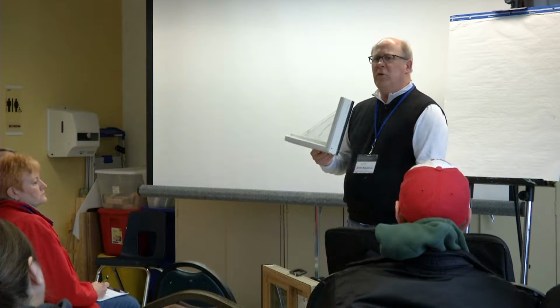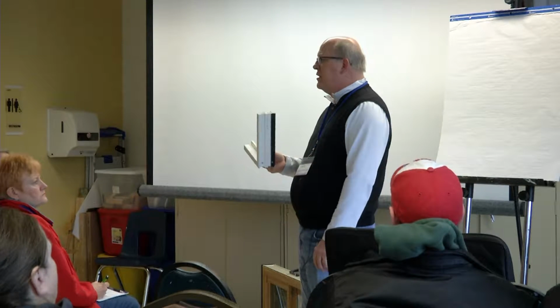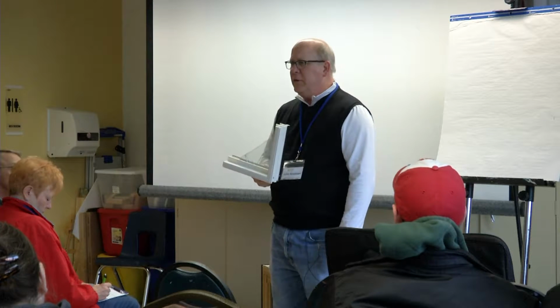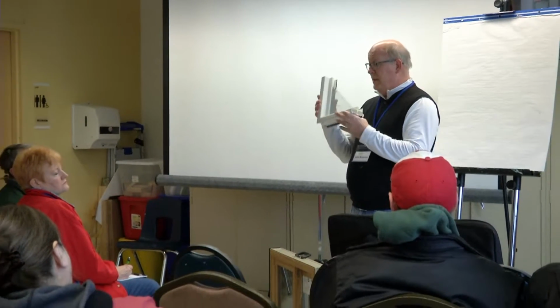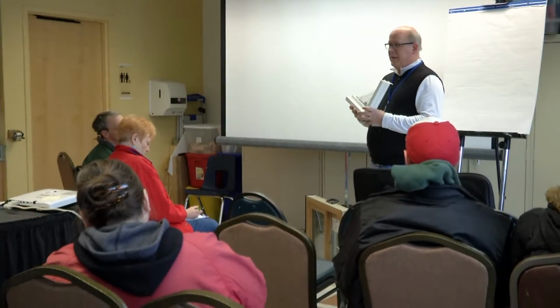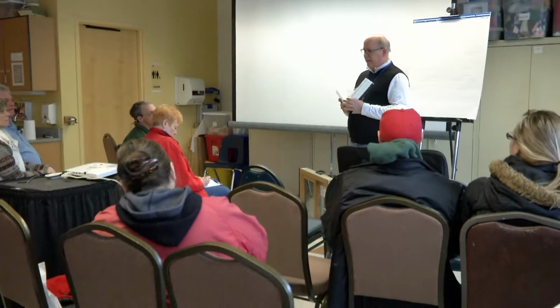Okay? So the reason you'd want to do fiberglass is that it's very strong, very durable. But it's not going to make things any more energy efficient for you, folks. 80% of our heat loss is through the glass in a window. 15% of our heat loss is through air infiltration, and another 5% of our heat loss is through conduction through the frame. So it doesn't really make that much difference what frame material I'm using in terms of the energy efficiency of the window. So this is for durability. It's not that it's going to make it any more energy efficient or anything like that.